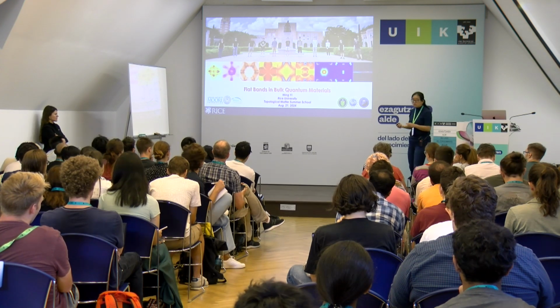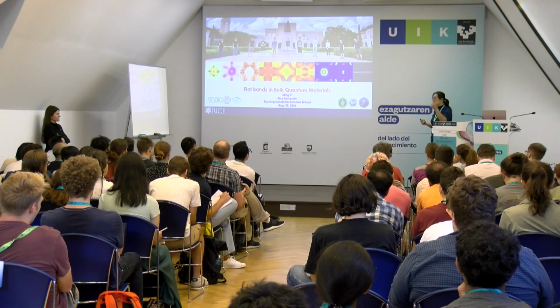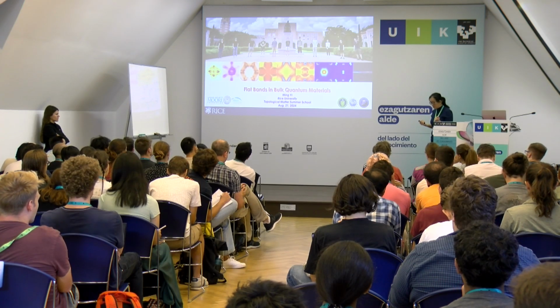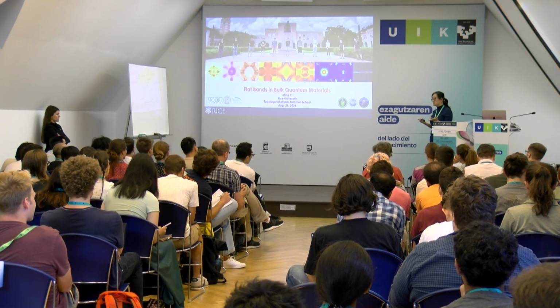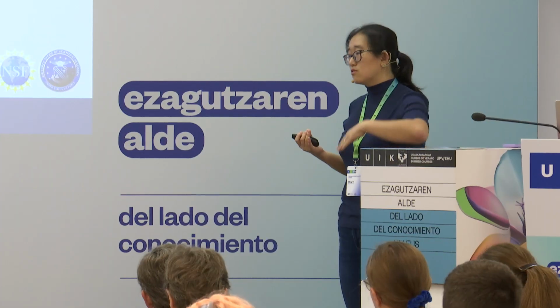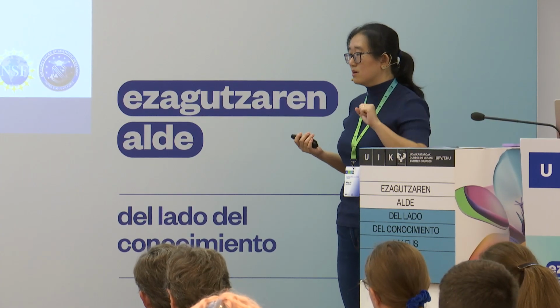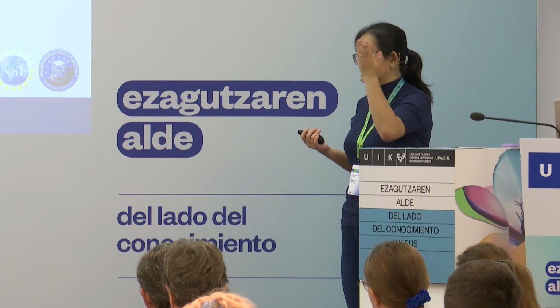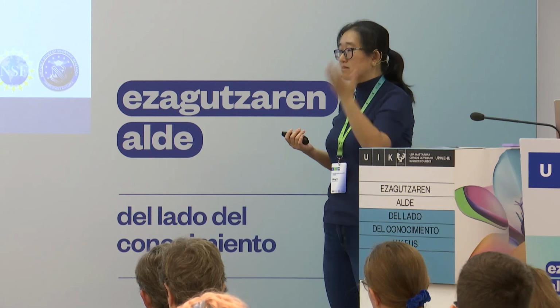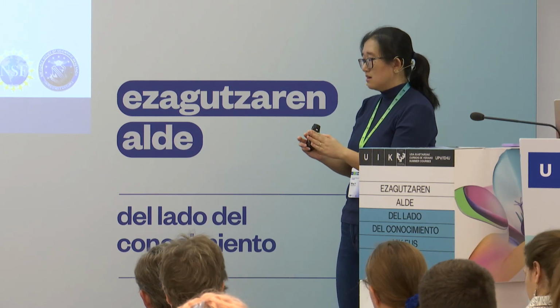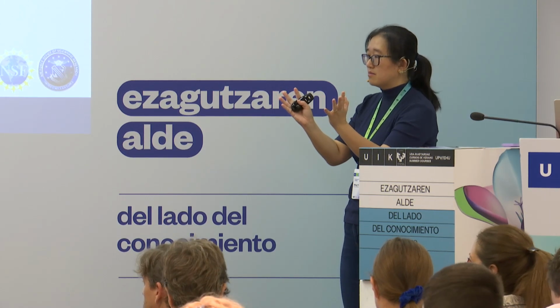That's a very good question. This depends on the photon energy. What you're probably thinking about is laser ARPES, where the photon energy is 6, 7 eV. After you overcome the work function, you have maybe 1 or 2 eV left. That's the dynamic range for the amount of kinetic energy you can measure. So that limits you to the zone center for most materials.